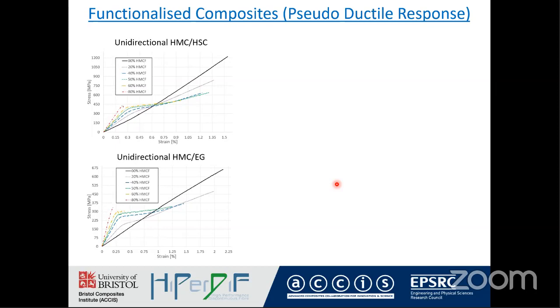a poor response in tension, or at least a rapid sharp failure in tension, and the need to try and produce a pseudo-ductile metallic-like response in failure. And as you can see here, in these two cases, the black line on the left-hand side, these are unidirectional laminates. In black, this is essentially a high-strength carbon, and in this case, the black is a glass composite coupon.